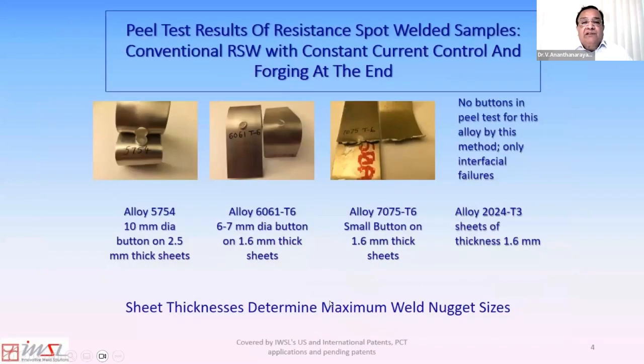If you look at efforts to spot weld these alloys using conventional methods that are used in the manufacture of, say, the Ford F-150 aluminum body, you can see that the 5000 series and 6000 series alloys give you very good buttons in a peel test of spot welded aluminum, whereas 7075 gives you some questionable buttons, and the breaks are mainly in the sheet metal. And with a 2024 alloy sheet, you cannot even get a good peel test done. The separation is entirely along the interfacial interface of the weld. So this shows the effect of the freezing range on the weldability of these alloys and why folks don't like to spot weld the 7000 and 2000 series alloys.